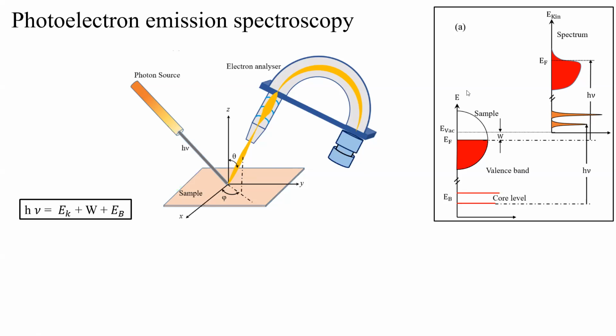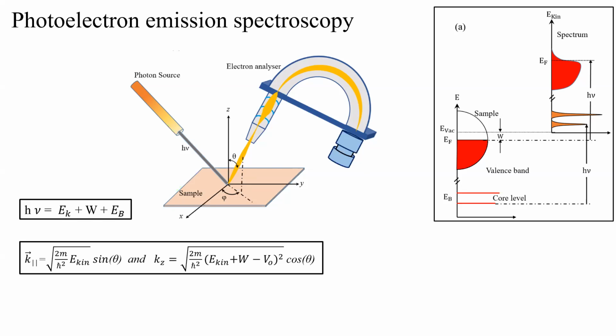Now, once you know the intensity as a function of electron kinetic energy, you can use this equation and then find out the binding energy. So you can get the intensity as a function of binding energy of different states. If you have also measured these electrons at different angles, which is basically the angle-resolved photoelectron spectroscopy technique, then in that case you can also calculate the momentum of the electron that is coming out from the sample.